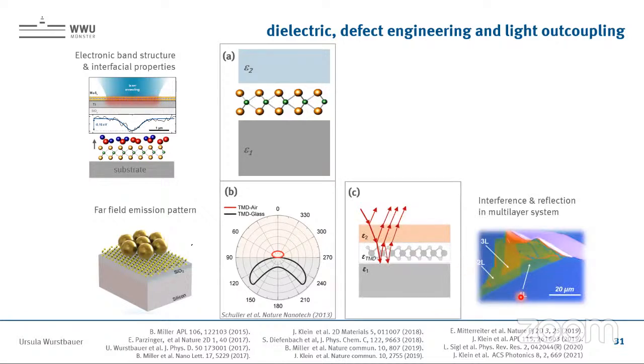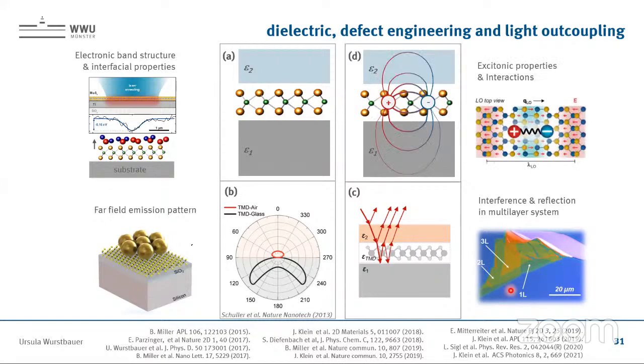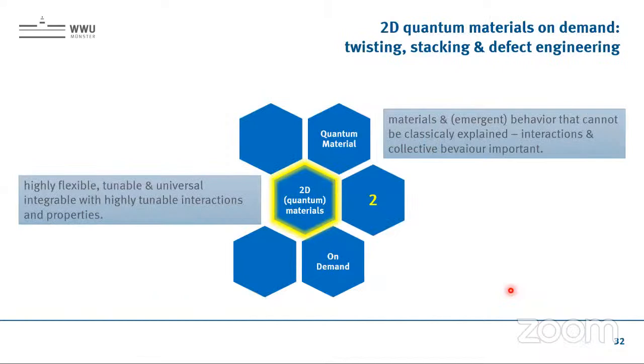Another example, which provides us with the fact that we can see those materials under the optical microscope despite being so thin, is the so-called interference contrast, in reflection and multi-layer systems, where we have multi-interference or reflectance at these interfaces, such that we can have constructive and destructive interference depending really on the thickness and the materials in the surrounding. And with that, we can have substrates where we can see those materials, as in this example, or where the materials are completely invisible. And of course, the excitonic properties can be changed as well. So with that, we now really have flexible, tunable, and universally integratable 2D materials.